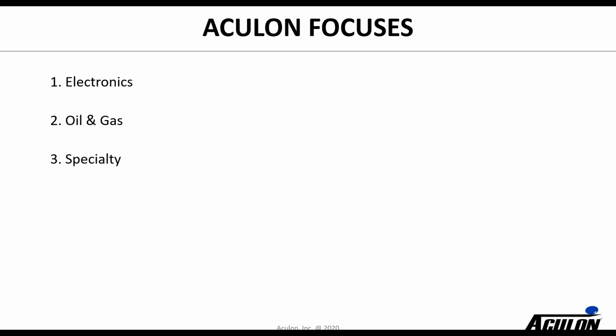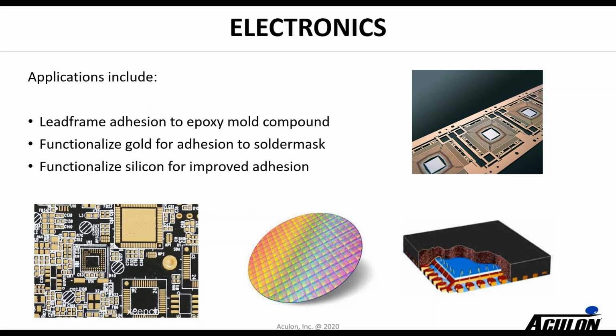The three main areas of the technology are sold into the electronics market, into oil and gas, and then what we call a specialty market, which is all-encompassing. In electronics, we've had some good success, especially with lead frames. Lead frames have both epoxy mold compounds that are bound as well as die attach, and we've been able to significantly improve adhesion with both mold compounds and die attach. Our treatments can modify basically all metals, including even gold, and so we've had good luck with adhesion of solder masks. We can also modify silicon, which is of course important in the electronics space. So our platform applies to silicon wafers.